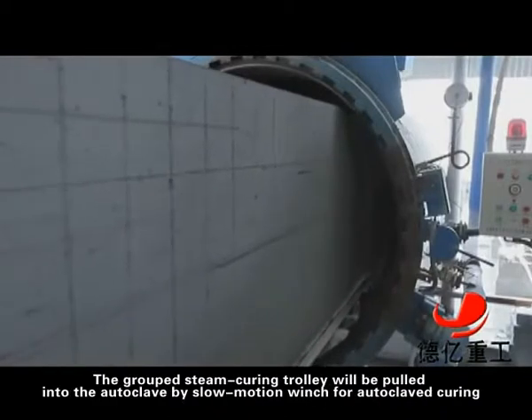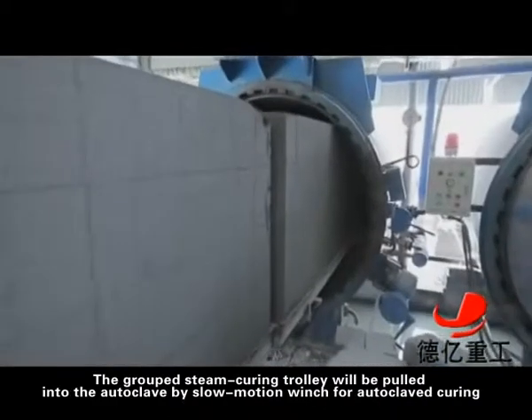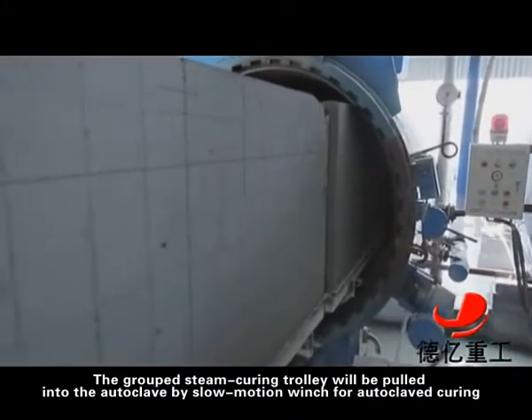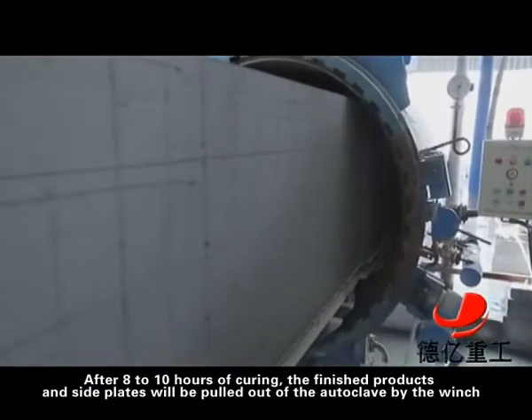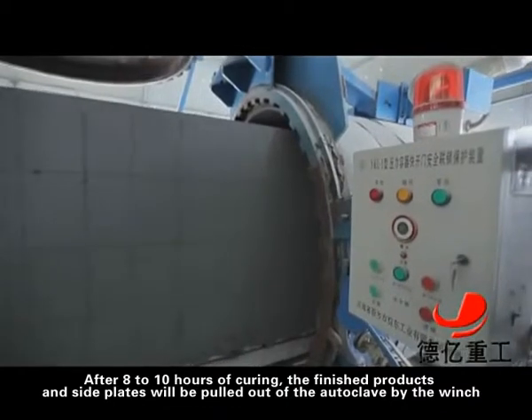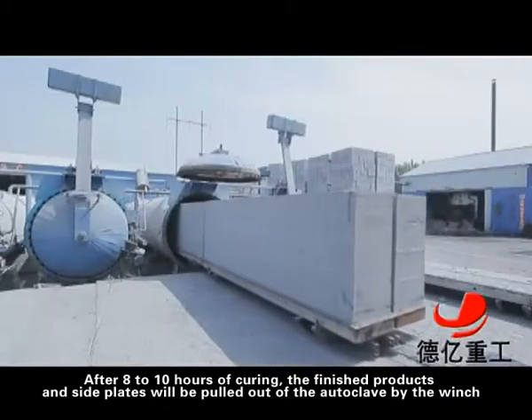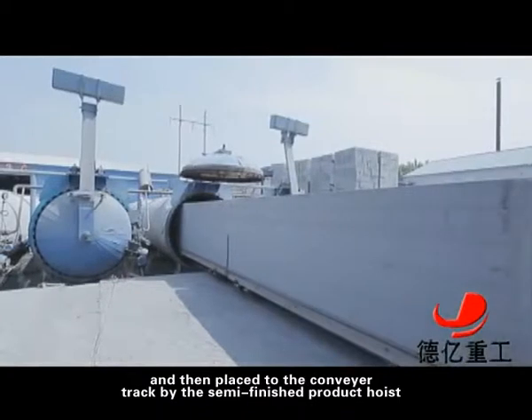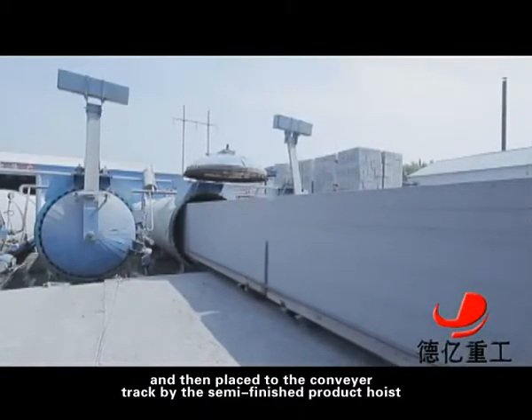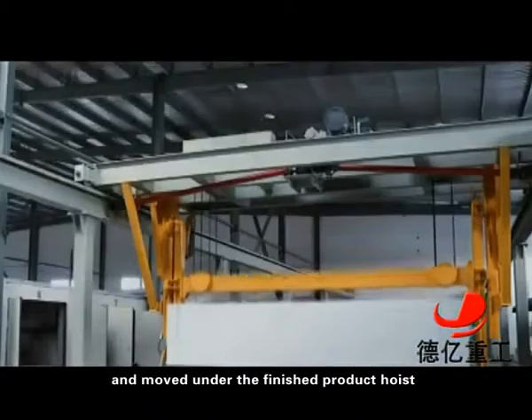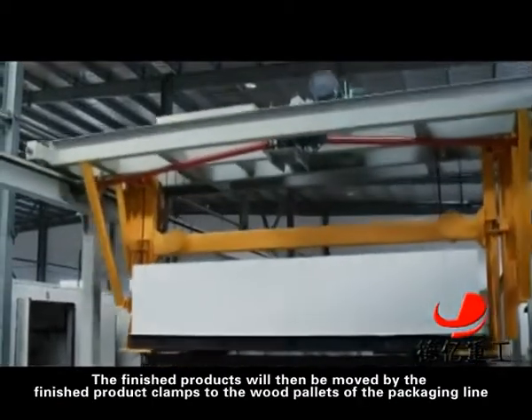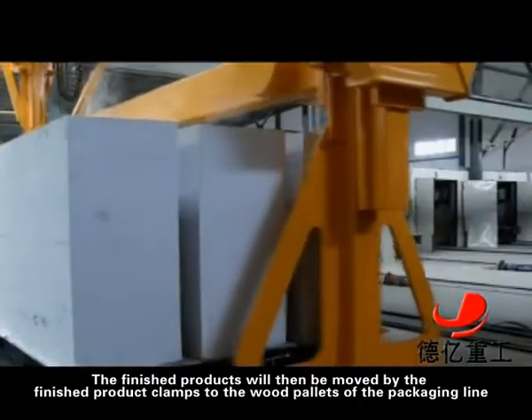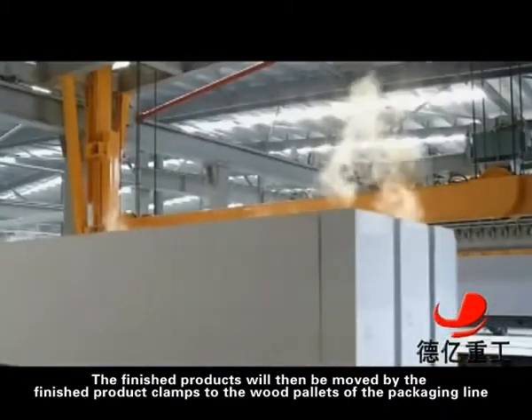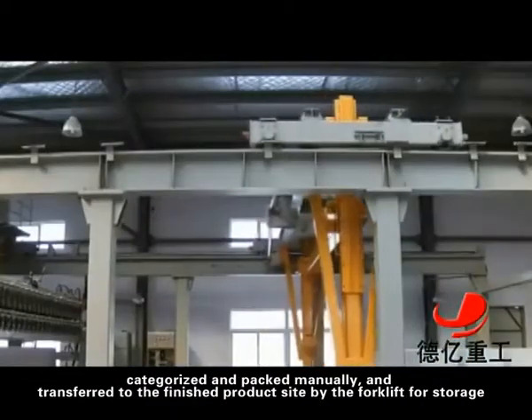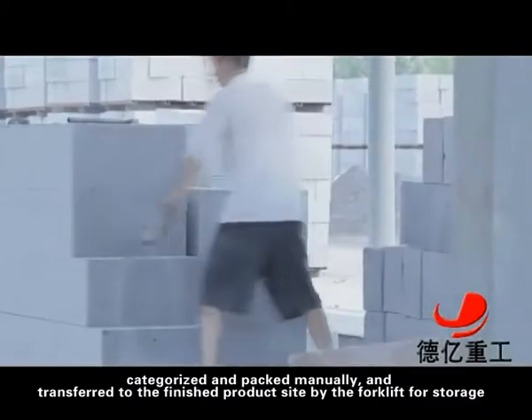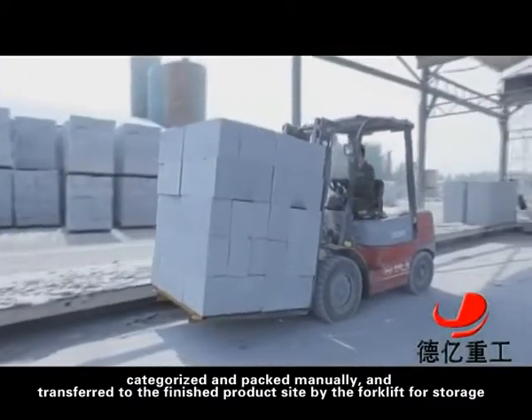The group steam curing trolley will be pulled into the autoclave by slow motion winch for autoclave curing. After 8 to 10 hours of curing, the finished products and side plates will be pulled out of the autoclave by the winch, and then placed to the conveyor track by the semi-finished product hoist, and moved under the finished product hoist. The finished products will then be moved by the finished product clamps to the wood pallets of the packaging line, categorized and packed manually, and transferred to the finished product site by the forklift for storage.